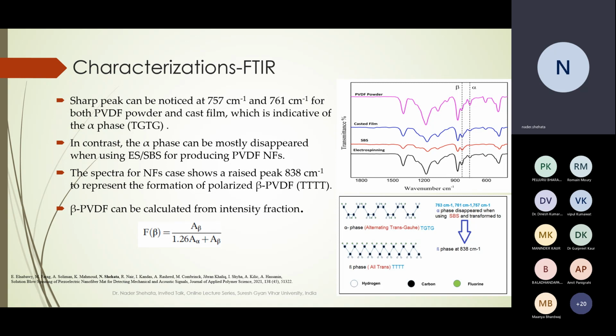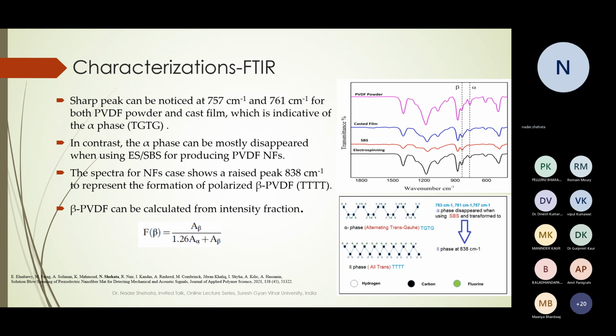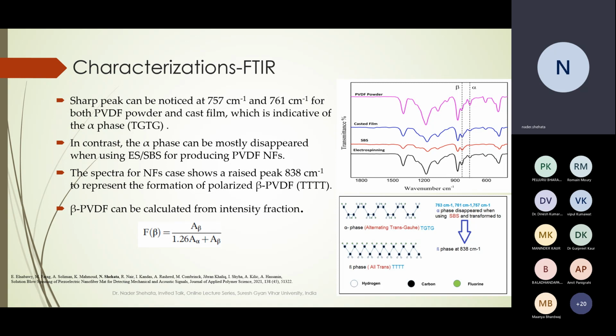Related to another technique, in some cases you may choose one of both, not necessarily using both techniques, XRD and FTIR spectroscopy. Again, for FTIR spectroscopy, the peaks of either alpha or beta phases could be shown as a pattern of peaks according to the vibration of the internal bonds inside the polymer. Consequently, you can calculate the ratio between the peaks of beta phase and the peaks of alpha phase, but this time you depend on the intensity of the transmittance, not the area under the curve. In this case, you can calculate the fraction of beta sheets formed in the material. As I said, it's highly preferred to have the highest possible beta phase. It will not reach 100%. Most likely it would be in the range between 80% to 90%, so that you can have quite superior piezoelectric nanofibers.